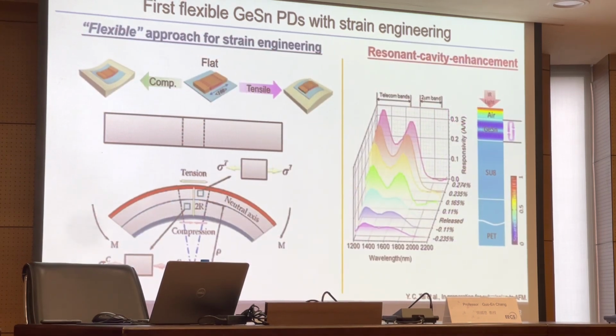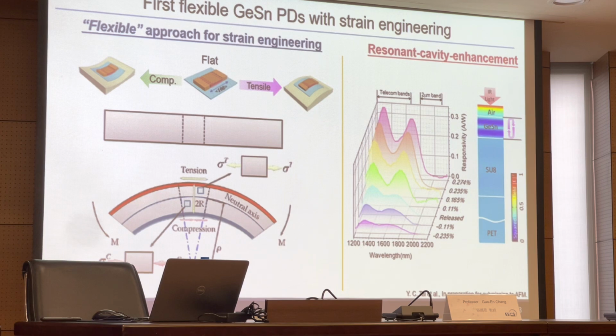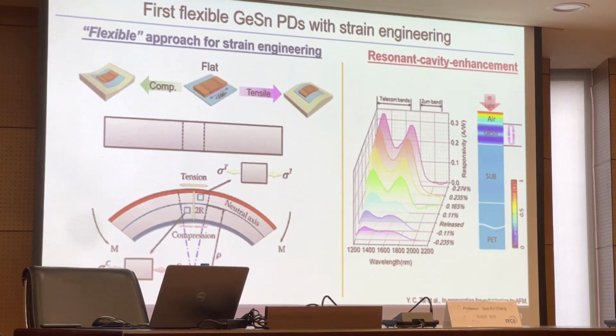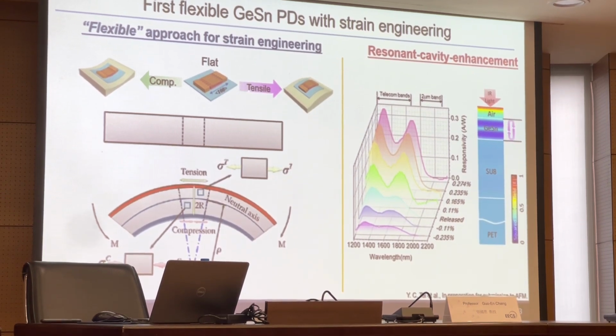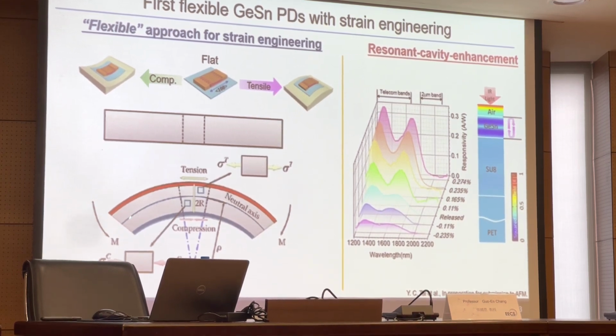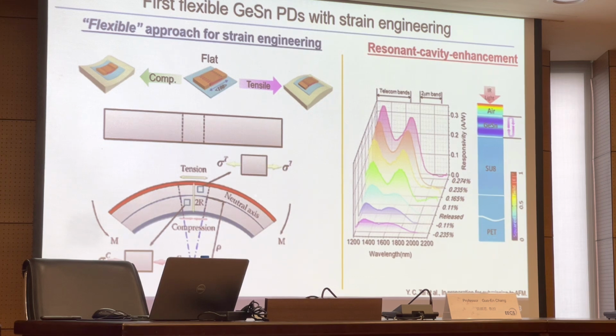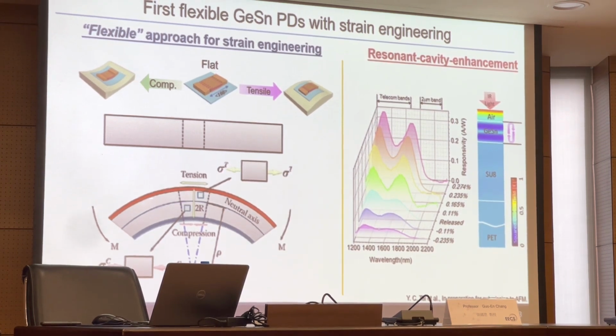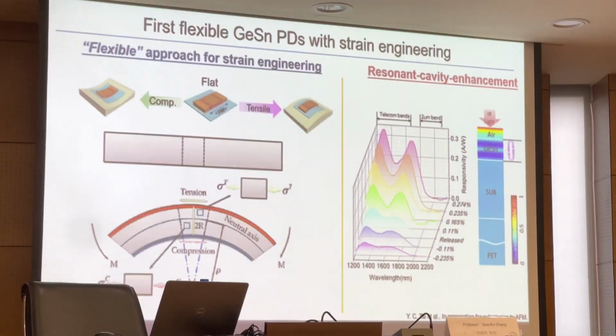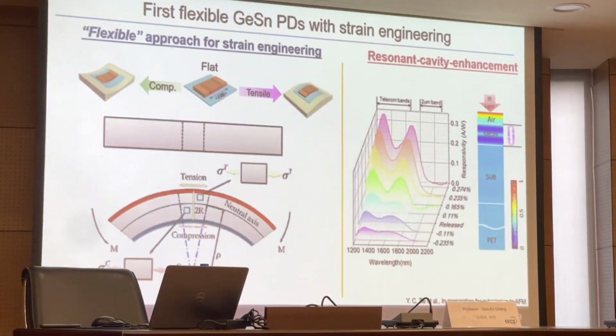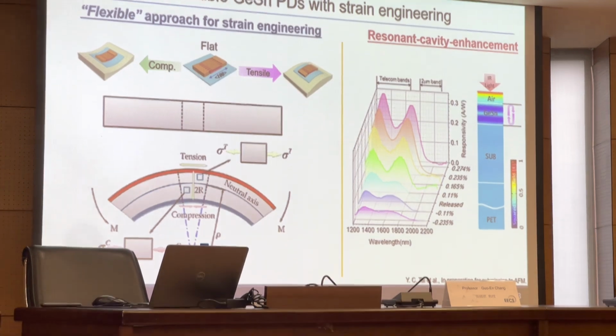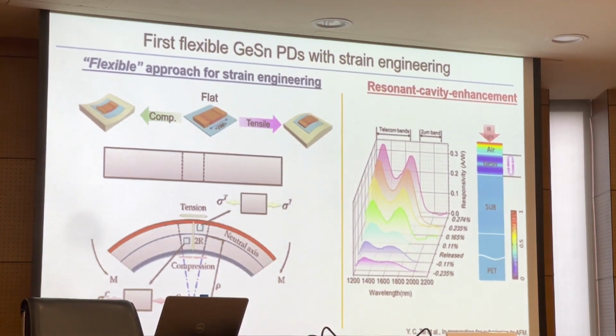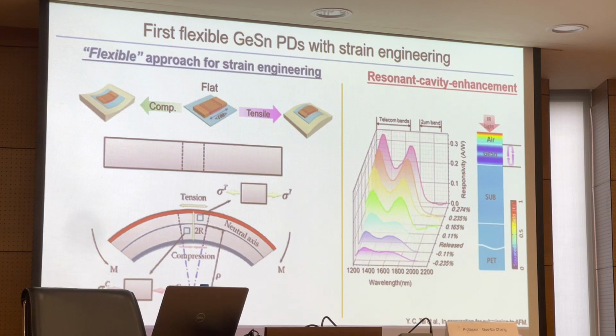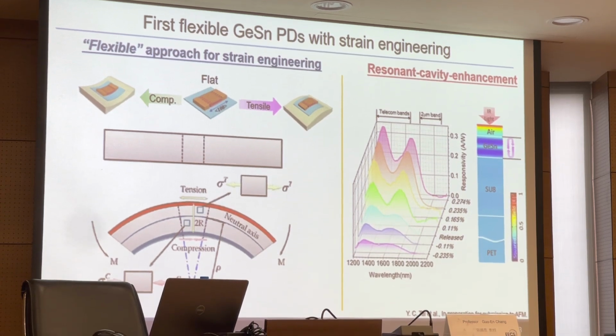Another more interesting aspect is strain engineering. When we transfer print germanium thin film onto a PET substrate, the structure is a very thin germanium layer on a very thick PET substrate. The germanium thickness is about 300 nanometers, and the PET substrate thickness is about 170 micrometers.